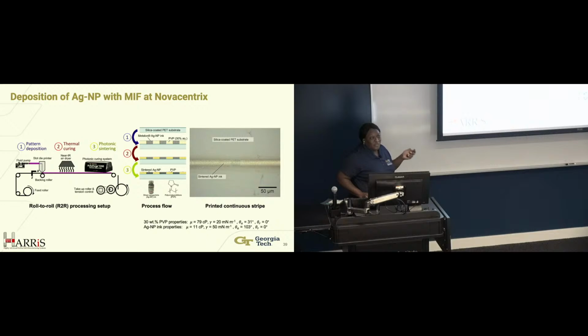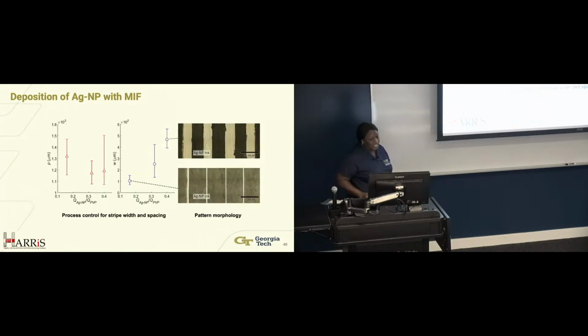That is the smallest feature that we know of using a slot die coating process. And it's stable, which means the reason this has less spreading is because almost immediately after depositing, we were drying, whereas with the PEDOT:PSS, we didn't do that. And so that's once it reached steady state. Adding another layer to our coating system, like this PulseForge system, we can get even more complex structures, shapes, and chemistries, process them continuously, and control the feature size.